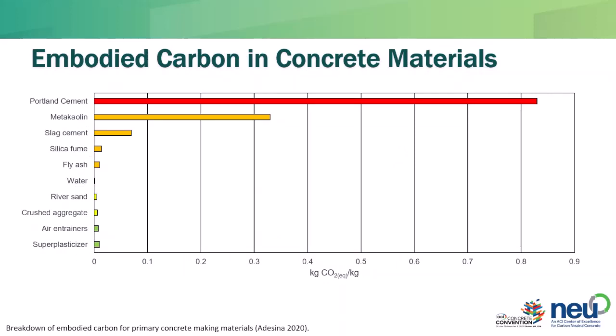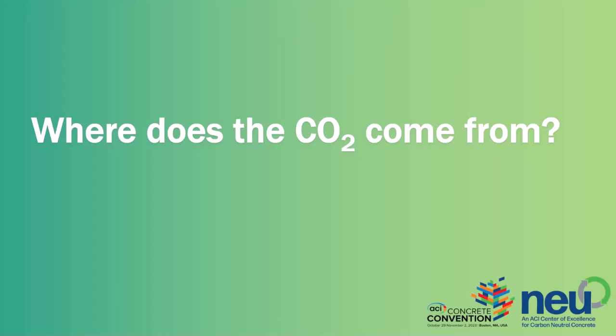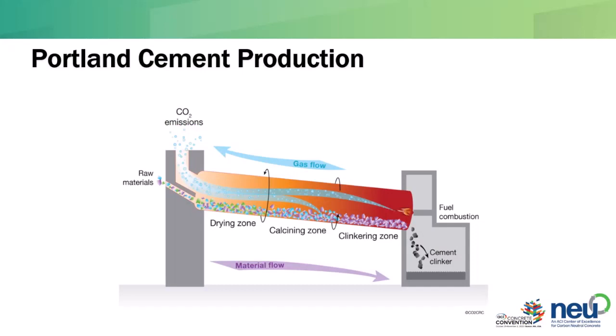If you look at specifically what the materials are in concrete that are causing this high carbon footprint, Portland cement, of course, is one of the highest ones, right? Compared to some of the other materials like metakaolin, slags, silica fume, etc. The aggregates, air entrainers, some of the other admixtures can be a little bit high, but Portland cement is largely the biggest target that we should be going after. So one of the questions you have to ask yourself if you're trying to reduce that carbon footprint is, where does the carbon footprint come from, right? Specifically, in the production of Portland cement, I think probably most of us know what this situation is here.